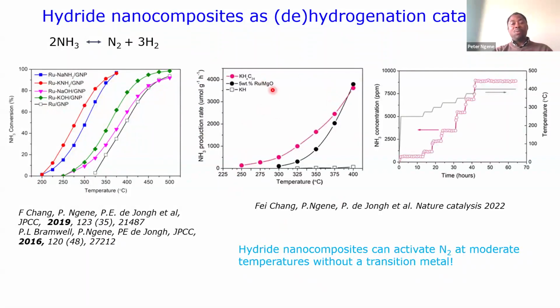And another wonderful one: can we now even make ammonia? This is a serendipity kind of experiment that shows that if we put potassium hydride inside a certain type of carbon, inside the pores, potassium hydride can convert nitrogen and hydrogen back to ammonia at moderate temperature, even better than ruthenium, which is the classical catalyst for making ammonia.